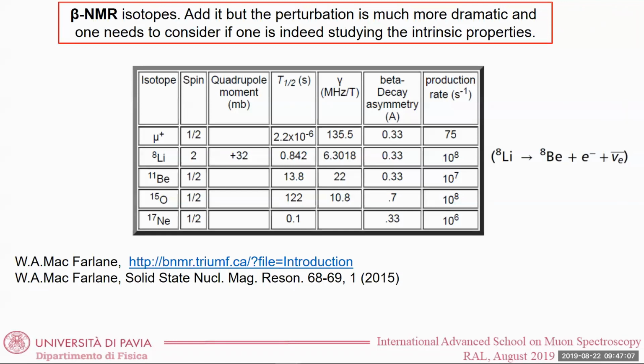The point is that you can measure these time scales. For example, in high-temperature superconductors, if you take the parent compounds, let's say La2CuO4, from the value of 1 over T1 you can measure what is called the Heisenberg exchange frequency, which is of the order of 10 to the 14. So you can access this time scale by measuring 1 over T1. Of course, you cannot measure at this very low time scale directly.